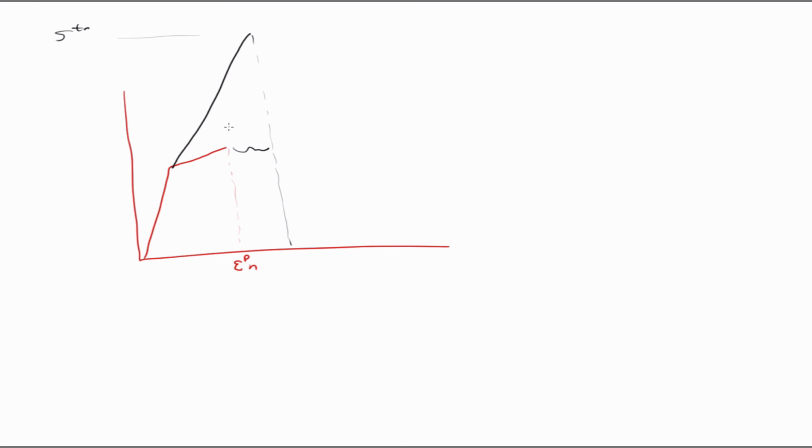Well, if it's pure shear, then the pressure component, if you have some compression, is going to affect the slope. So the way to test it is to set beta equal to 0 and see if the slope of that line is h. That verifies that the hardening is working properly.